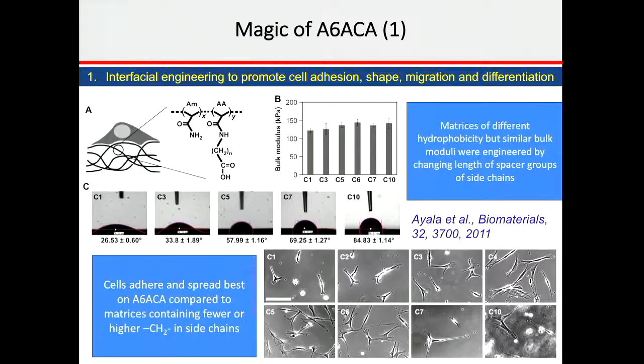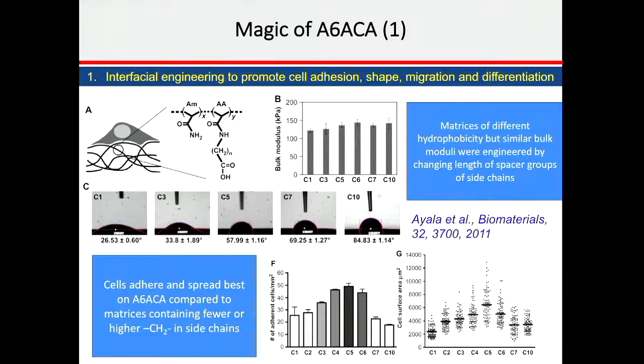But if you see the others, for example, it is much less indeed. So there is something very interesting that is happening here. If you see, for example, the way the cells adhere and spread, they spread based on A6-ACA. If you see the fraction of adherent cells, C1, C2, C3, C4, C5, C5 is actually the top. And if you see, for example, the cell surface area, again, it is C5 which is the best. So A6-ACA somehow or the other seems to be doing the magic.